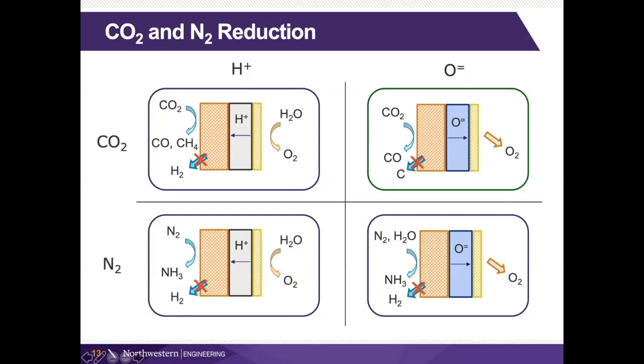In the case of nitrogen reduction, you have this challenge again of hydrogen evolution, but it is one that I think is sort of a holy grail and one that is really worthwhile to pursue. In the case of oxygen ion conductor, you really wouldn't try to do this because you have to pull oxygen away from this water molecule and then convince that hydrogen to react with nitrogen in a way that doesn't allow just hydrogen to evolve. So this is pretty unlikely. This is actually almost commercial level already.